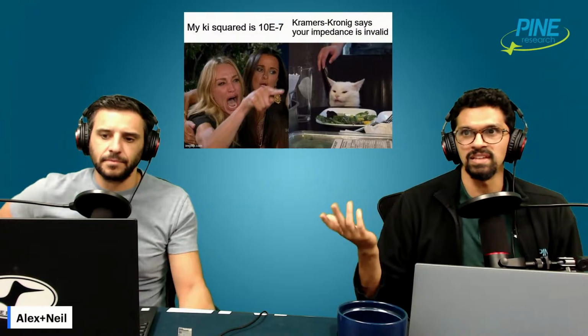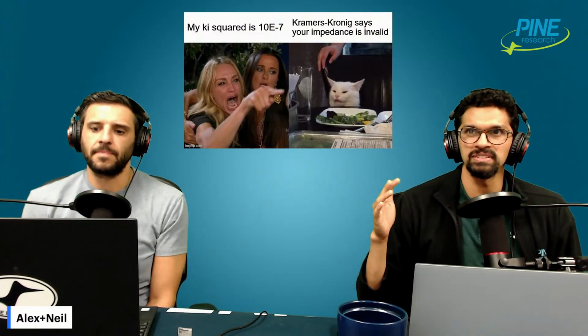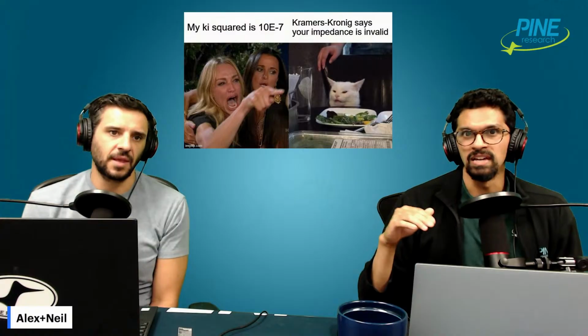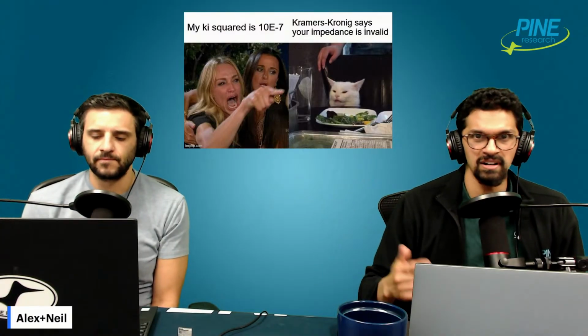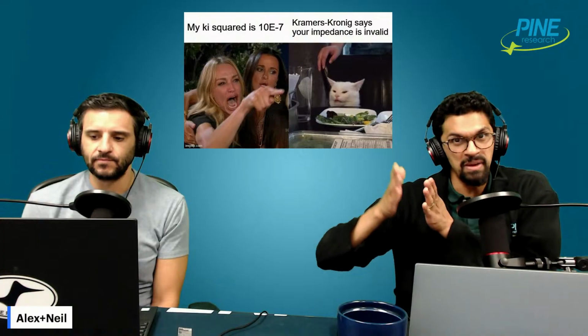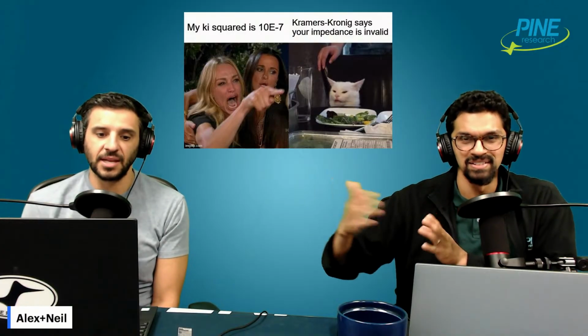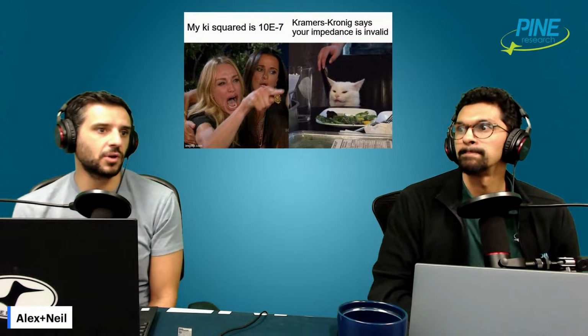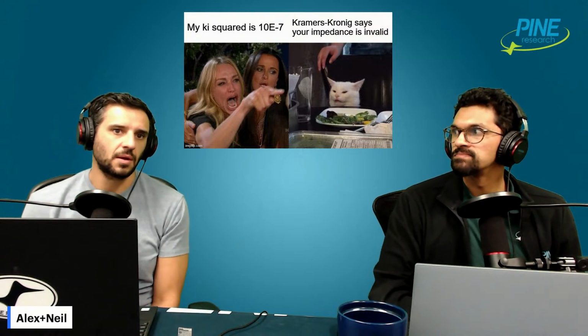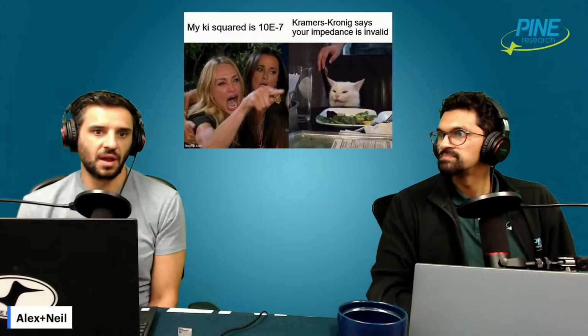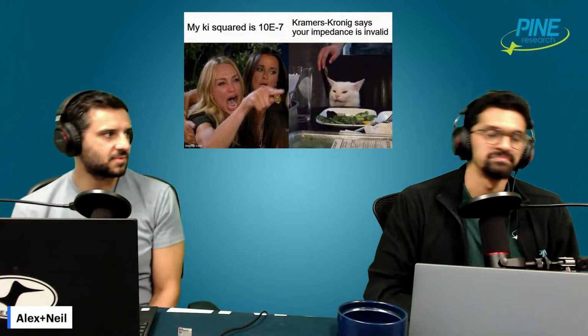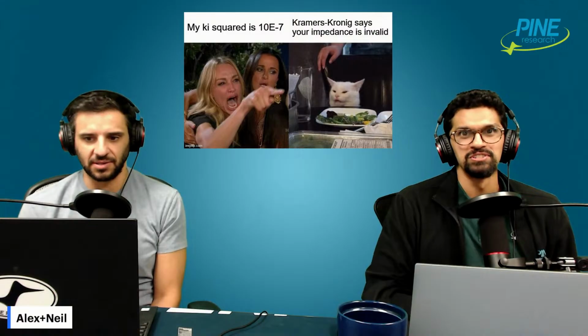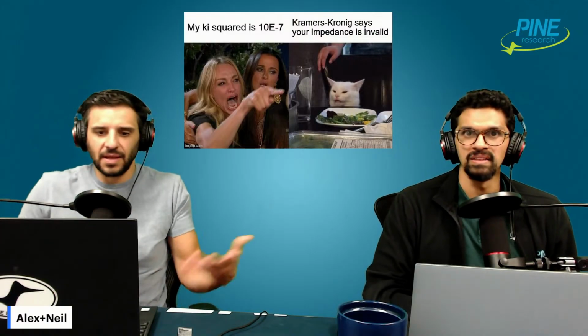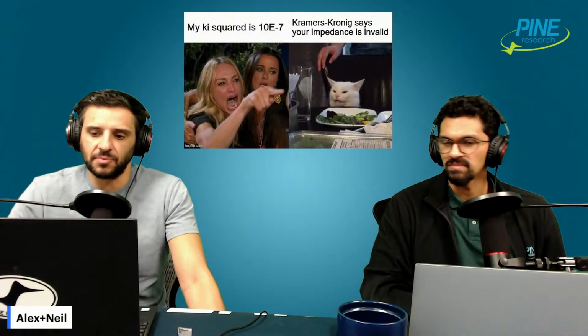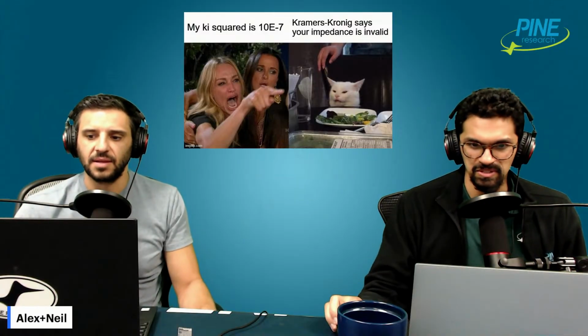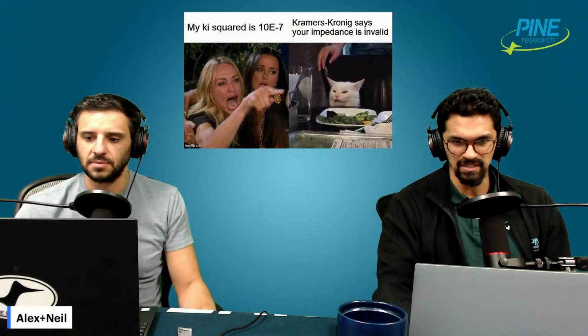They were making some points that you kind of get the best results every 10 millivolts or 5 millivolts. If it's 20 or 50, it's a little bit harder in terms of accuracy, because you may only have a 50 millivolt window, and it depends how many points your instrument is giving you. If your potentiostat software, for instance, is measuring points every 5 millivolts, it's hard to get slopes accurately. You have 2 points, right? So it's not ideal. Some of that will be determined by your instrument as well. But anyway, that's just a quick thing I wanted to point out. I thought that was interesting.